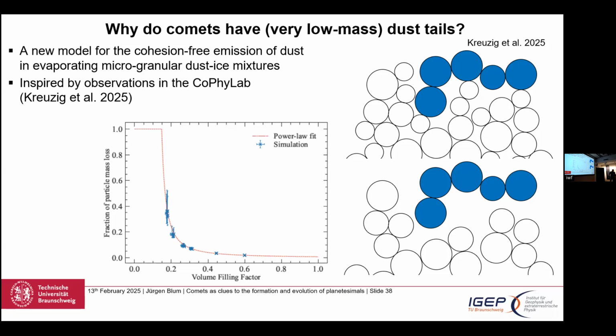The environment is vacuum and it's cooled. So all the particles shrink. And of course, the smallest ones shrink faster because they have a larger surface to volume ratio. So at some point they are gone. You're seeing that this particle is no longer here. All the small particles are gone. So if in this plot we just have 3 sizes, the smallest are gone first. Then come the next and the next, and so on. And this cluster here, and this is why it's marked blue, this cluster has no contact anymore.